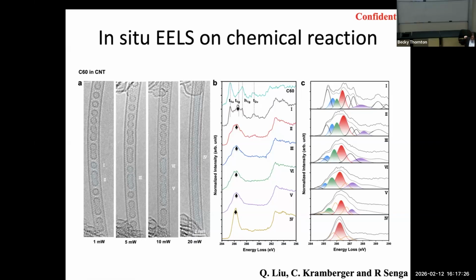We could follow all the small changes of the carbon K edge if we have some monochromators. This is a bit difficult for us, because we try to push the possibilities of spectroscopy with high spatial resolution, high energy resolution, and also time resolution. It's a very complicated experiment, but once you decide what you want to do, we could do that.